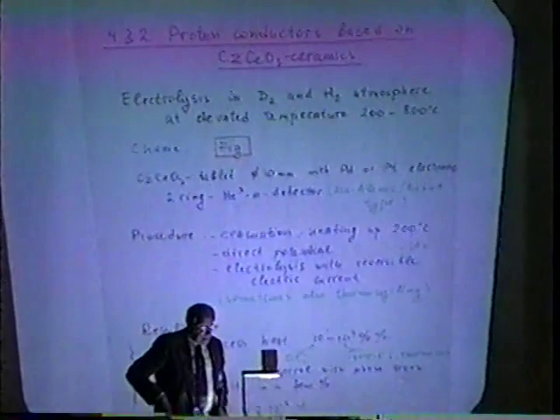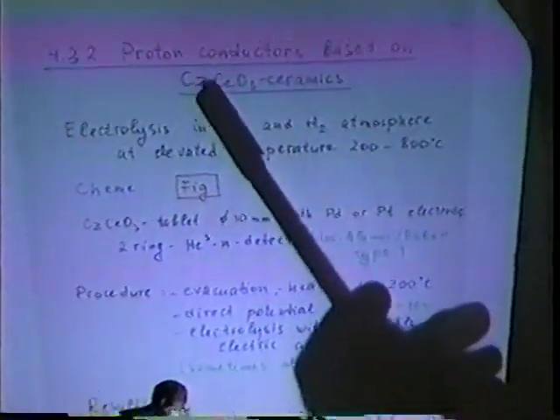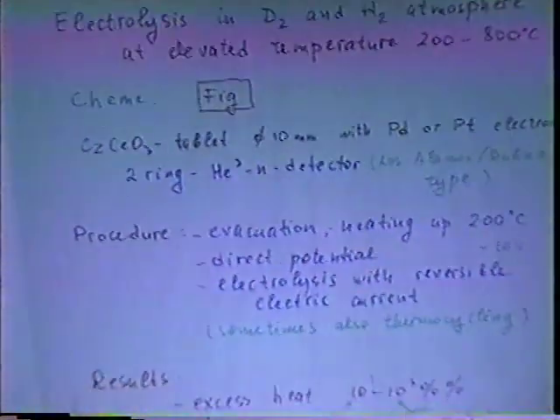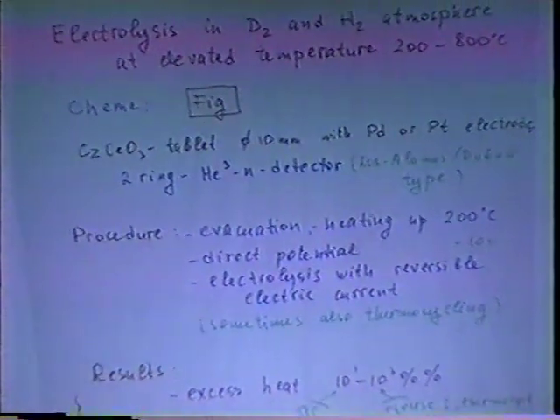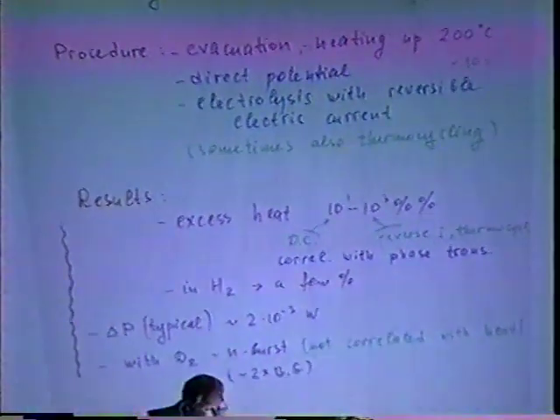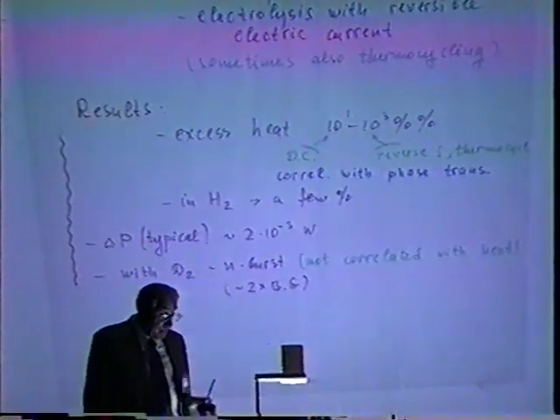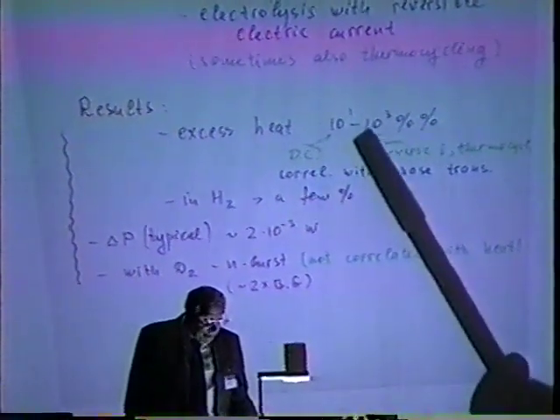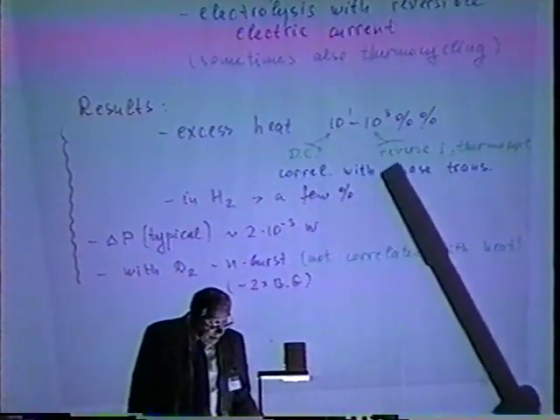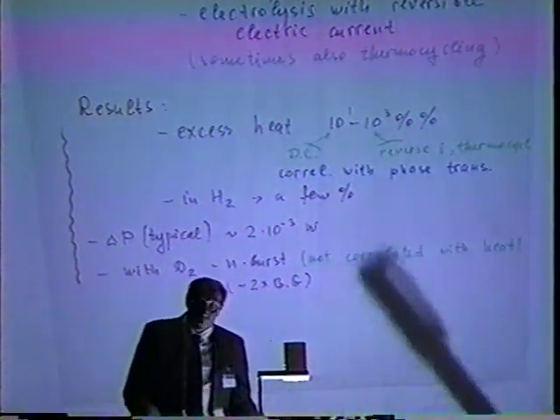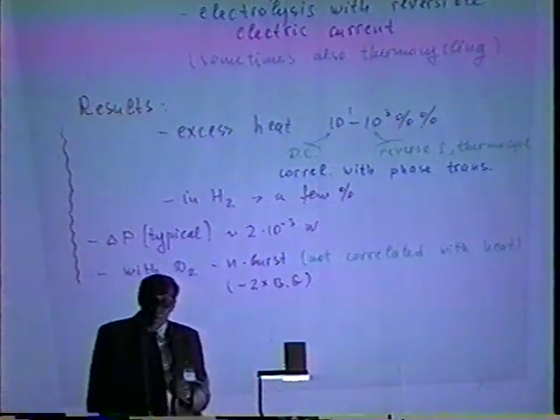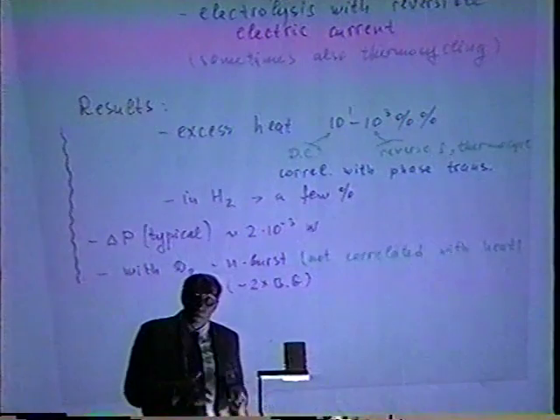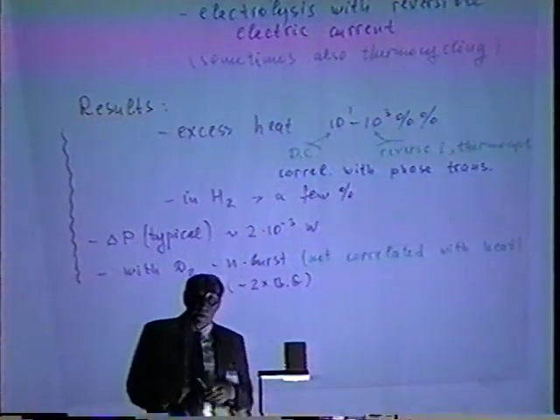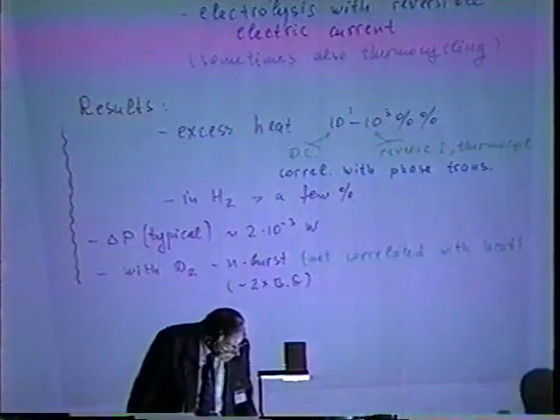The same group presented some interesting results with ceramics. I will not describe their procedure. Let me just show their results. They observed that there is excess heat which varies in different situations from 10% to about 1000%, 10% for direct current and much larger for reverse current, and sometimes they also use thermocycling. They believe that they observed a phase transition in this material for the first time, and they believe that this effect is related somehow to the phase transition.